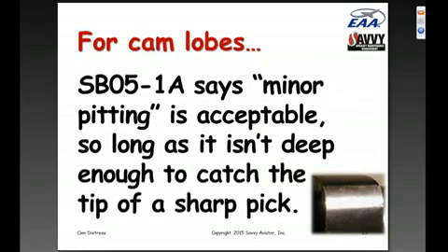Now for cam lobes, it's a little bit more complicated. But basically what Continental says about cam lobes is that minor pitting is acceptable so long as it isn't deep enough to catch the tip of a sharp pick. So what they're saying is that if a mechanic sees any pitting on the cam lobe, he should probe the pitted area with a sharp pick and determine whether those corrosion pits have significant depth to them so that they would catch the tip of the sharp pick. If they don't, then the cam can be continued in service. If they do catch the tip of the sharp pick, then the cam is considered unairworthy and the engine's going to need a tear down.